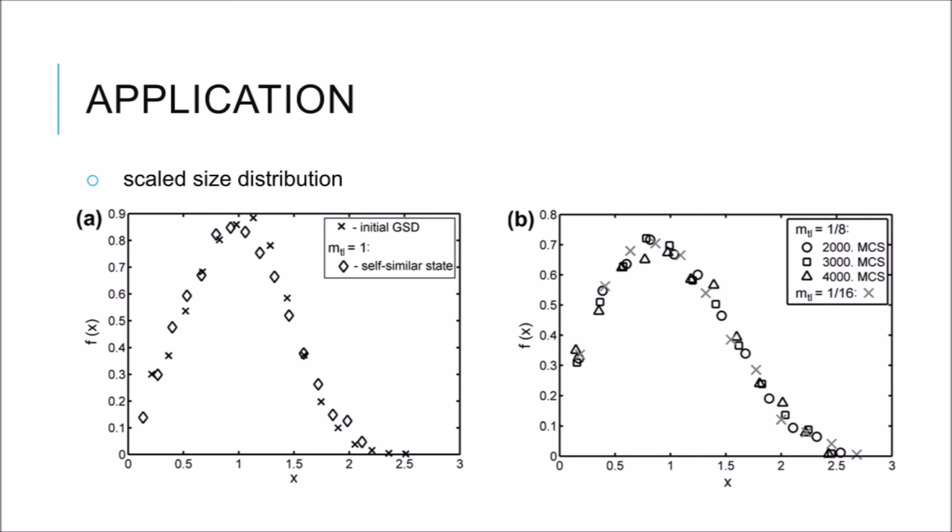So we do have this linear growth kinetics, and in addition we see that also the size distributions show self-similarities, meaning this scaled size distribution does not depend on the annealing time. But its shape is completely different compared to the one that we see here on the left.